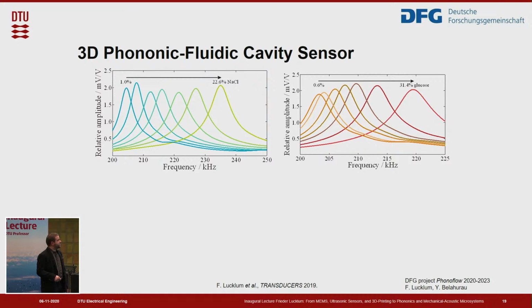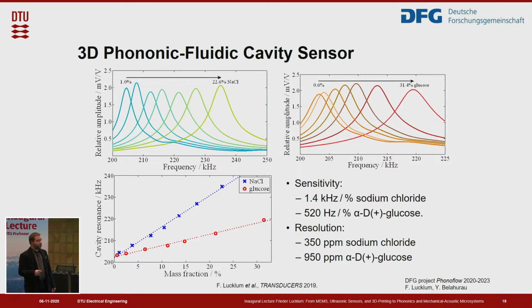And for an optimized initial design, we can see that we can use this as a concentration sensor to measure the concentration, for example, of salt and sugar in a water solution over a very wide concentration range. This basically covers the complete solubility range of salt and sugar, which is something that other types of sensors often cannot do. They are good for very low concentrations or good for very high concentrations, but covering the complete range is relatively unusual. And we also have a very linear relationship between the concentration and our resonance frequency. And the achieved sensitivity and resolution of this device is quite competitive compared to other results of acoustic devices found in the literature.